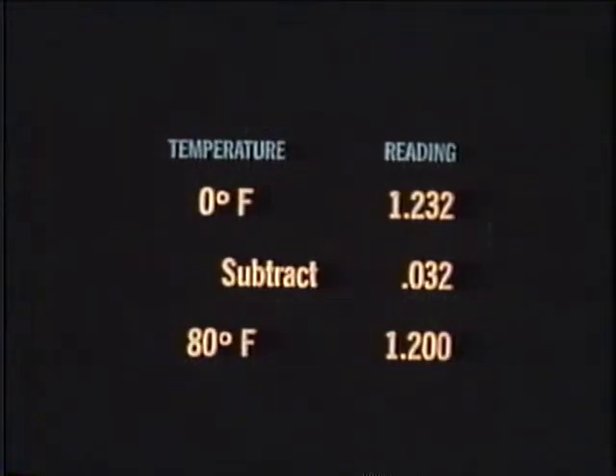To illustrate further, place a thermometer into the electrolyte to measure the exact temperature. If the temperature is 0 degrees Fahrenheit and the reading 1232, the gravity corrected to 80 degrees Fahrenheit is 1200. Thus, the true state of charge, 1200, is much less than is indicated by the hydrometer reading of 1232.